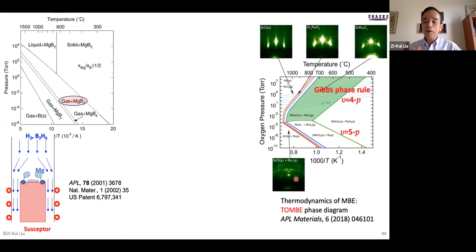We saw this diagram is very interesting, very useful for the MBE. We call it the Tombe phase diagram, some call it the MBE phase diagram. That was published in 2018 because we found it so strange. But of course, the bottom line is because ruthenium solid is not stable anymore when the partial pressure of oxygen goes high. So the oxygen partial pressure versus total pressure is a very important concept when you deal with gas phase. We learned a lot from this one.